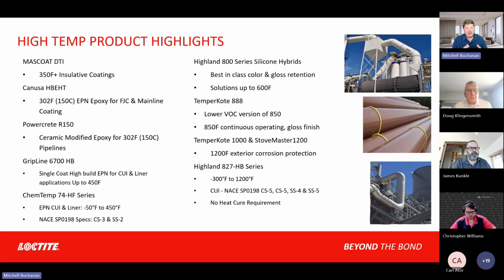Then we get into our higher temperature. Now we're moving out of the organics into the inorganics, and we've got the silicone hybrids, best in class color and gloss retention type solutions up to 600 Fahrenheit continuous operating. Step up from that, we have the TemperKote 888, which is a lower VOC version of the TemperKote 850, and those are going to be 850 Fahrenheit continuous operating with a gloss finish option. So good if you want that nice, pretty appearance.